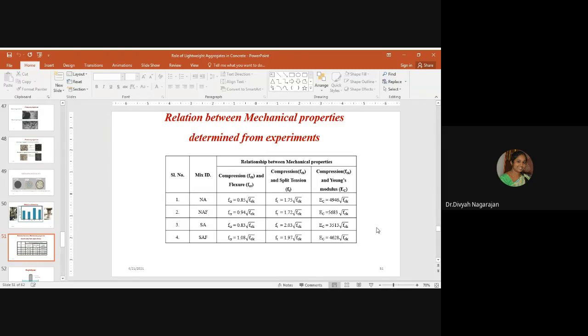Similarly, the modulus of elasticity. The modulus of elasticity for normal weight concrete is 5000 root fck as per IS code provisions. But for the normal aggregate concrete developed in the laboratory, it was 4946 root fck, and addition of fiber drastically increased the modulus of elasticity to 5683 root fck. For sintered fly ash aggregate, it was around 40% less when compared to the normal aggregate concrete. It was 3513 root fck, and when fiber is added, the elastic modulus increased to 4628 root fck.